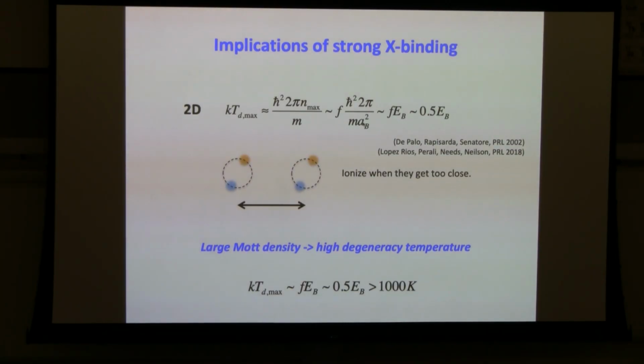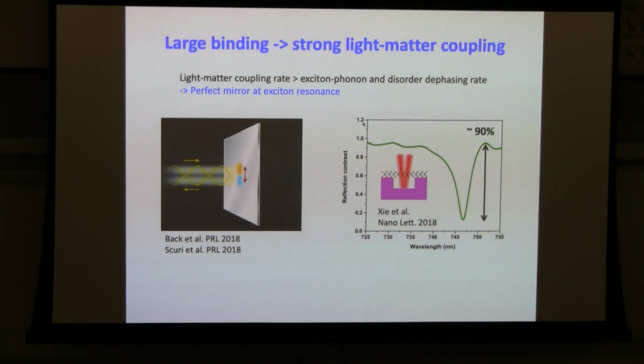So there's plenty of room for you to reach a pretty high temperature exciton superfluidity in this kind of system, in principle. Right? So this looks too good to be true, and anything too good to be true is usually not true. So the problem is that the very large excitonic binding will also mean a very short excitonic lifetime, because of the strong light-matter coupling in the system. In fact, the light-matter coupling in this system is so strong that the light-matter coupling rate exceeds all the other dephasing rates from the other channels, such as exciton-phonon coupling or exciton disorder dephasing rate.